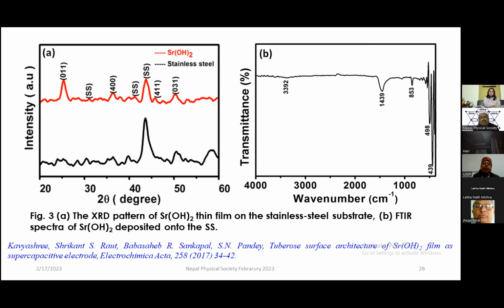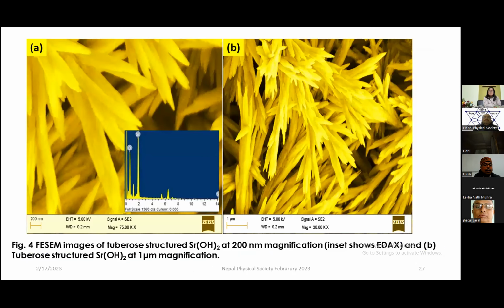Then we can come to the SEM. SEM analysis is also a very important one to see the surface. One can see this surface morphology, the FESEM image of the tuberose. It has a very beautiful structure, that tuberose morphology. It exhibits high porosity, and porosity is a very important aspect.